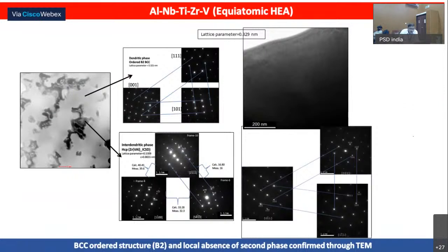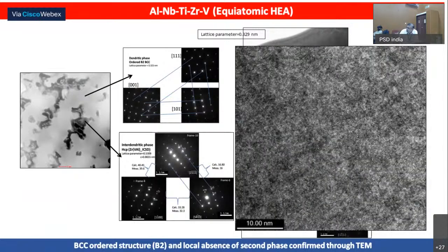When we did the TEM analysis, there was a very minor second phase. The primary phase was generally BCC structure, and the secondary phase was showing some HCP structure. If you take the high resolution electron microscopy, I'm very sorry for the slightly poor image, I'm not able to resolve it here.